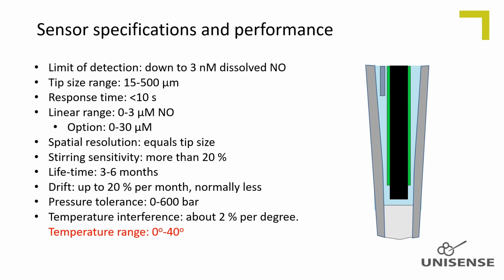At higher temperatures, the baseline and noise level increase and compromise the sensitivity. The temperature influence on the baseline is huge and much larger than other Unisense sensors. Therefore, temperature control, especially when working at temperatures above 30 degrees Celsius, is of extreme importance.